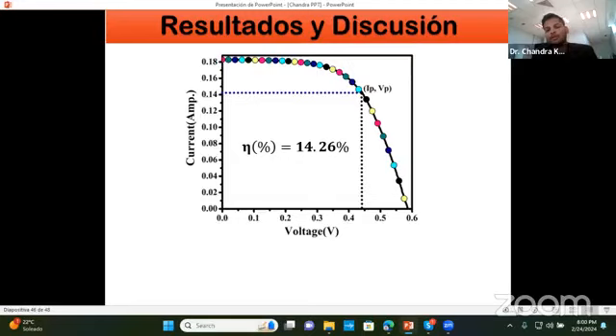If we are using either P-type material or N-type material, and also different passivation layers, different metallic or metal oxide layers, we further plan to use silicon with a perovskite layer. Very recently we are going to start silicon with perovskite, like a heterojunction of silicon and perovskite, towards a tandem solar cell. Reported work indicates that this could be more promising these days.